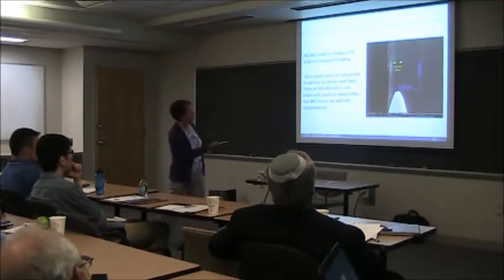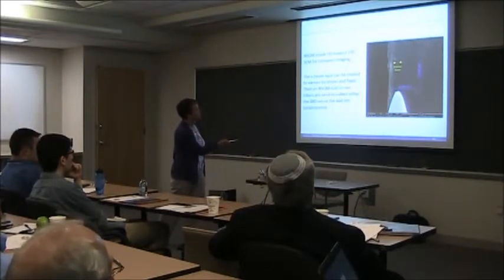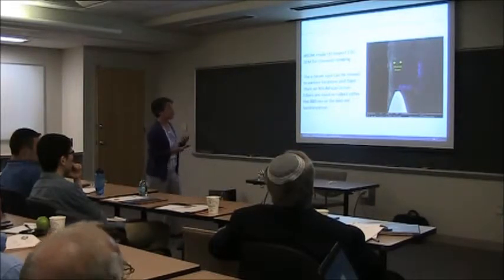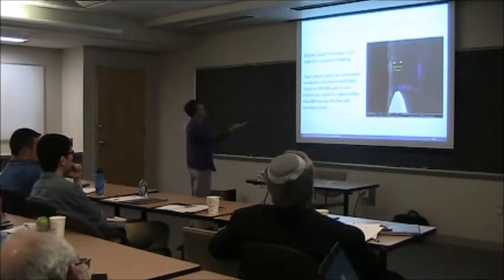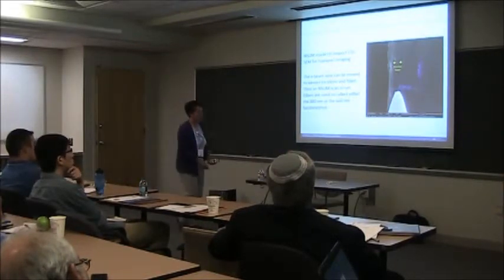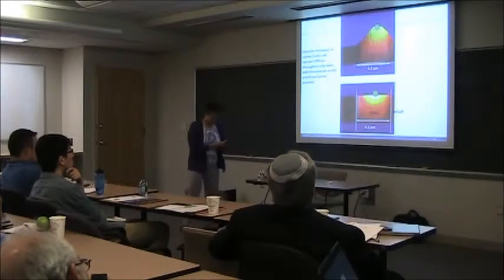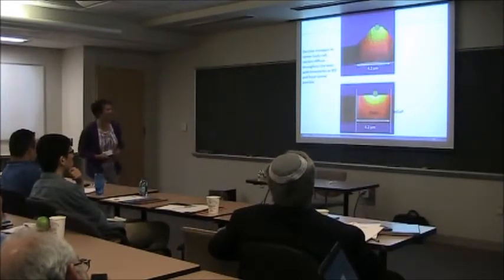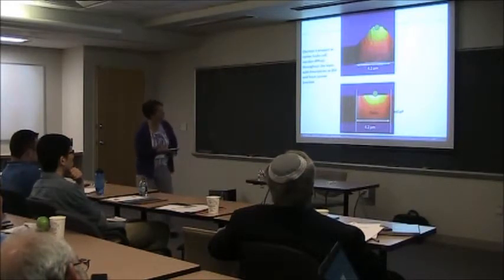So here's the structure in cross-section. The contrast is a little better than I can see here, but the gallium indium phosphide layer is here, the gallium arsenide layer is here, and my electron beam is going to go to either of those positions, and then the tip is going to come up and look at the luminescence from excitation at those points. And again, I'm going to use some filters so I know which wavelengths I'm looking at. This work is very recent, and I'm still talking to my collaborators, so I can't show you too much of it, but just a little bit of a teaser here.